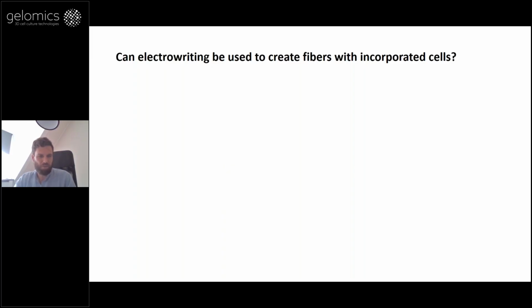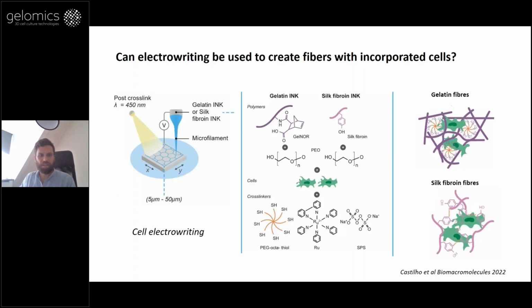We are also looking at this technique as a tool to further study what are the mechanical forces that induce cells to lay down collagen. And we believe that the shear forces and the tensile forces that we expose cells to in this, what we call cell electrowriting process, are interesting and the foundation for laying down aligned collagen. So basically what we did was look at two hydrogel bioinks, in this case based on two polymers with different gelation chemistries, gelatin and silk fibroin.